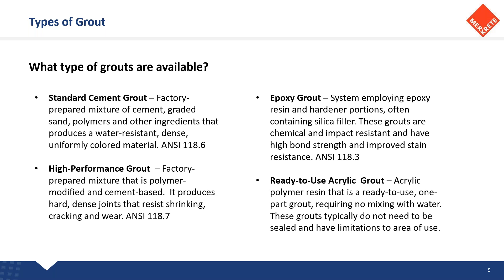Sometimes in high performance grouts it's going to be a calcium aluminate, hydraulic cements, and some other types of polymers and pigments. These help resist shrinking, help resist color getting blotchy or washed out, they're a little less sensitive on water mixture, and they're going to dry denser, harder, and sometimes faster depending on the manufacturer. I've always said that if you go back 10 years ago, people didn't really want to spend money on a more expensive grout, so they went with the standard cement grouts.